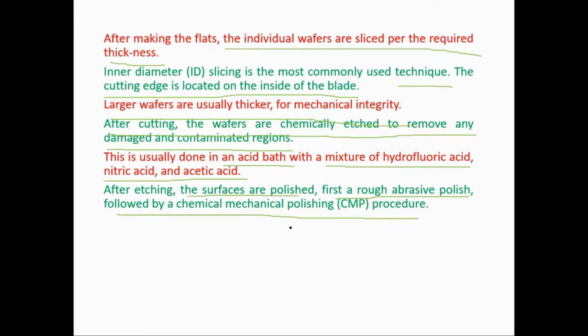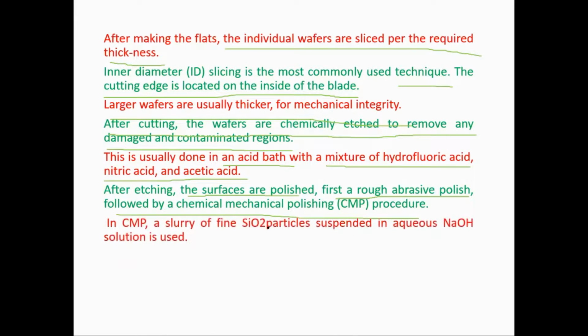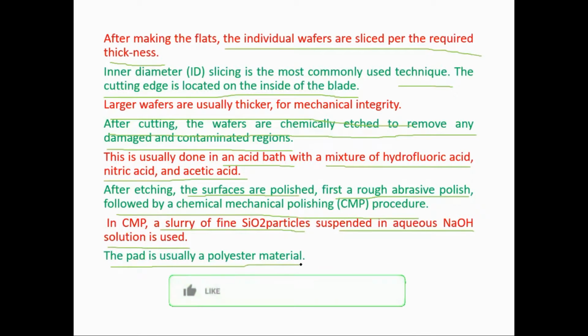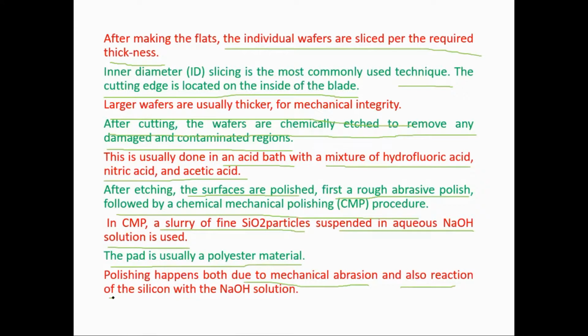Lot of dust is involved. Here we have different abrasives, but the procedure remains the same: they are polished so that the smoothness is restored. When you call it chemical mechanical polishing, it is a slurry of silicon oxide, SiO2, particles, used with sodium hydroxide solution. The pad used for polishing is a polyester material. Polishing happens both due to mechanical abrasion and also reaction of the silicon with the NaOH solution.